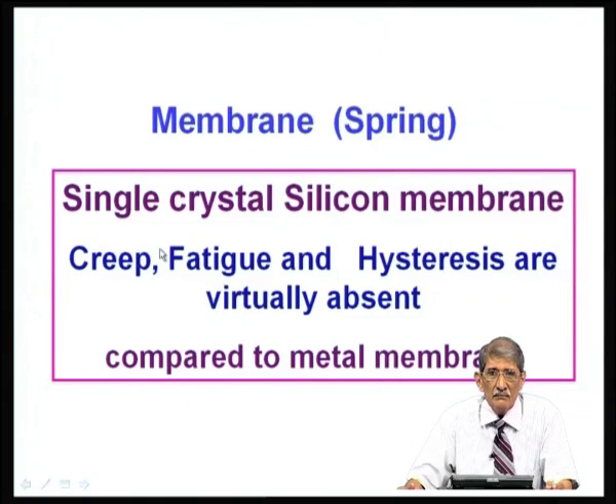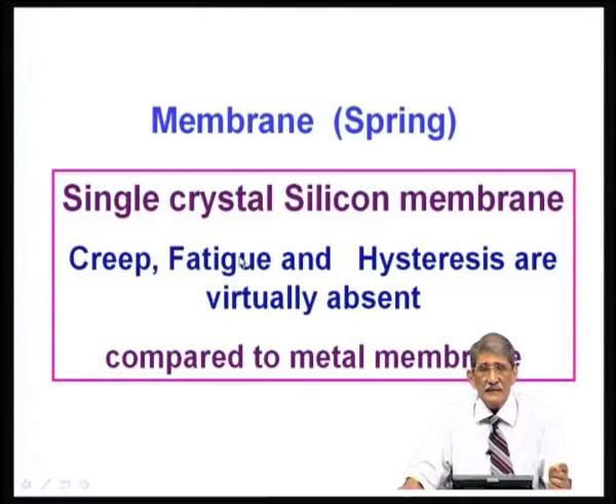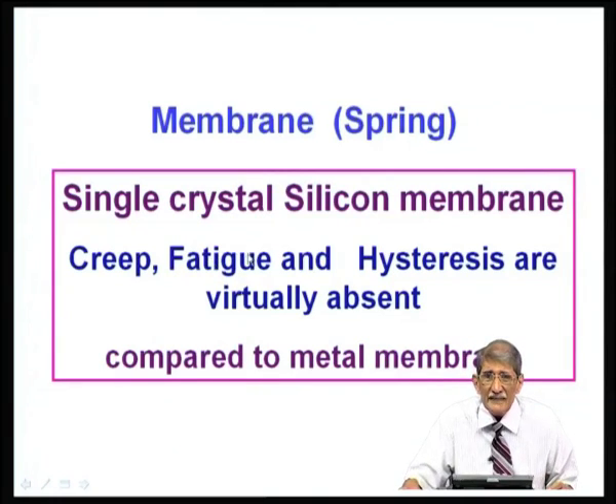The creep meaning, what is the implication of creep? If you heat most of the materials like metals, you heat it to almost slightly above half that melting point, there is a chance of there being warpage of that membrane. Whereas, silicon melting point is 1410 degrees centigrade, you can go right up to 1200 degrees centigrade, there is practically no warpage. So, that is what is meant by there is no creep.